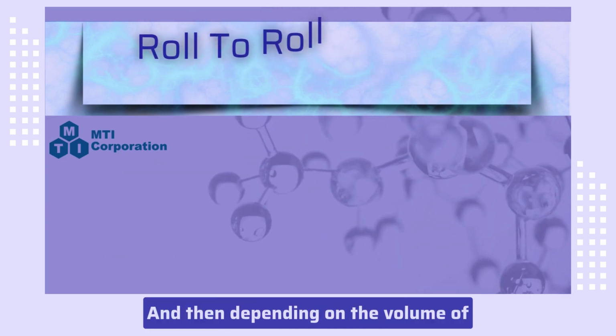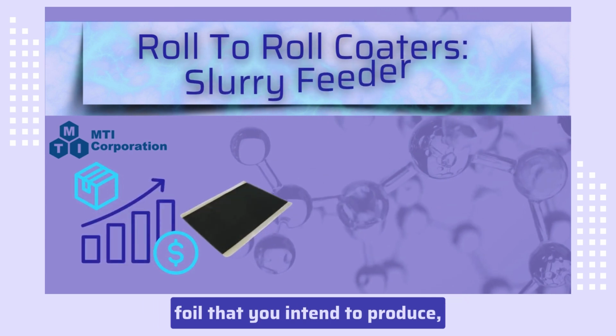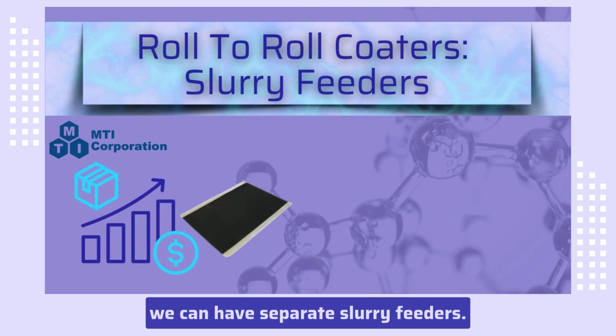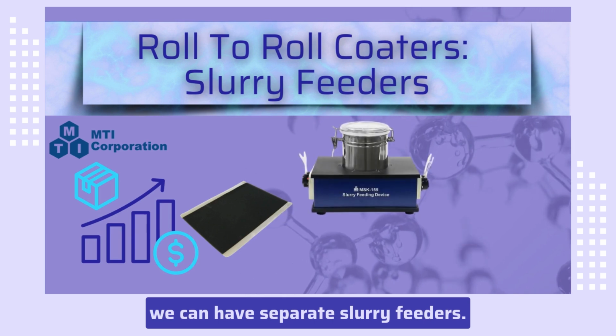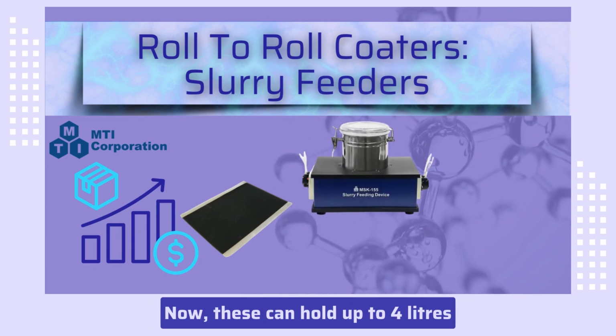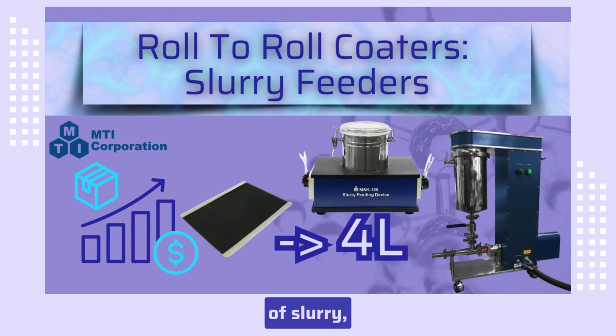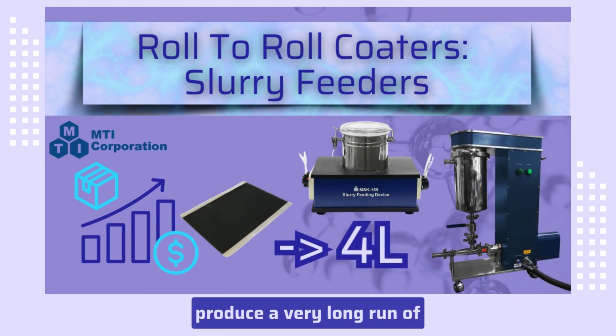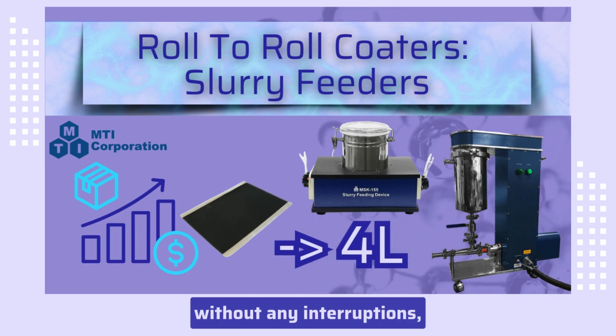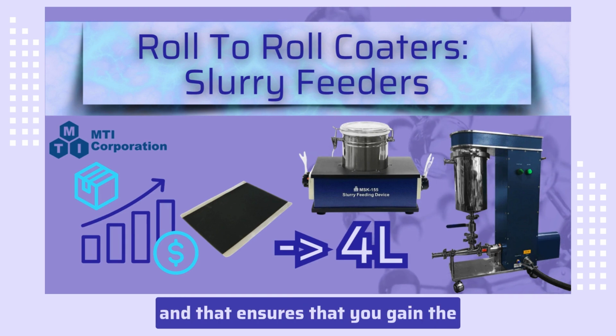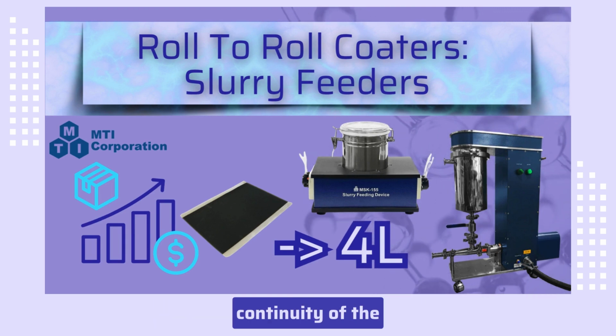And then depending on the volume of foil that you intend to produce, we can have separate slurry feeders. Now these can hold up to 4 litres of slurry, so you can produce a very long run of production without any interruptions, and that ensures that you gain the continuity of the coating method.